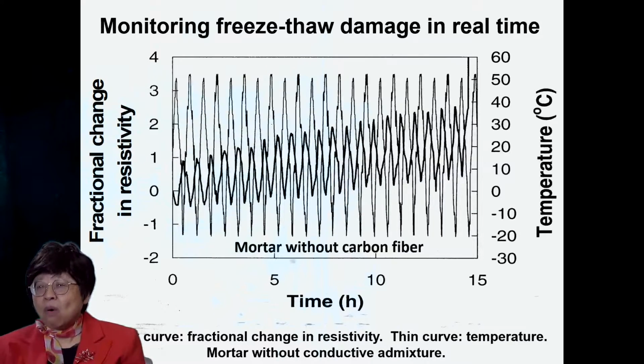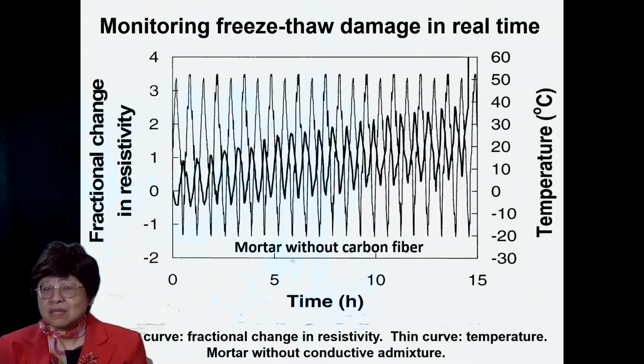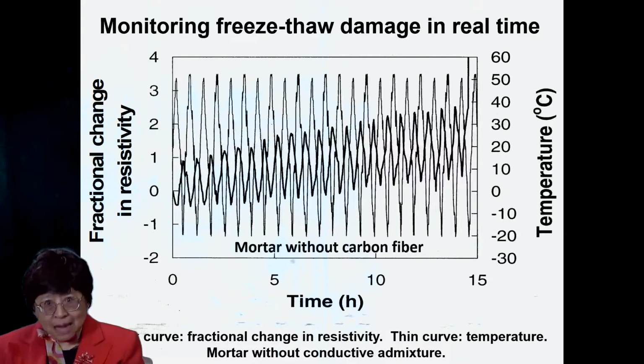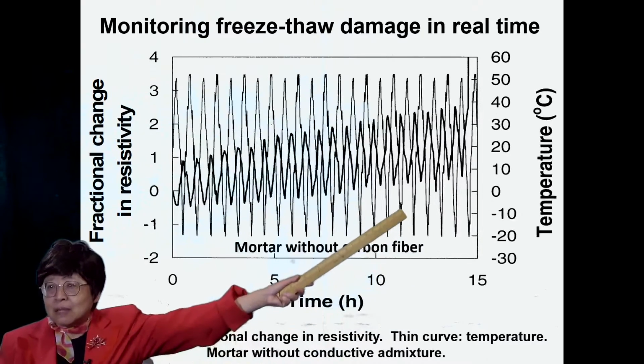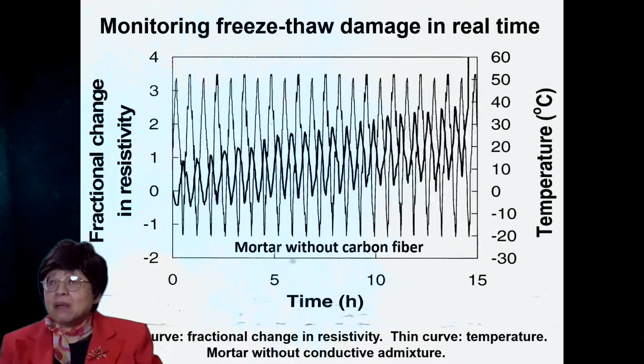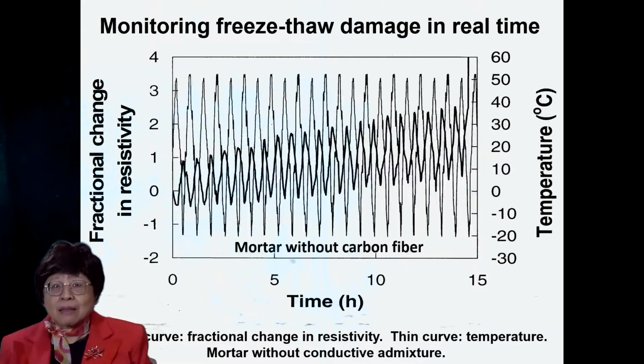And every time it warms up, the resistance goes down. And that is because there are interfaces. And upon increasing the temperature, the chance of the electrons jumping across the interface increases, thereby reducing the resistivity. And note that the baseline resistance incrementally increases in every freeze-thaw cycle, meaning that there is additional incremental damage inflicted at every freeze-thaw cycle. And at the very end of its life, the resistance shoots up, and that shooting up occurs at the coolest point of the last cycle.